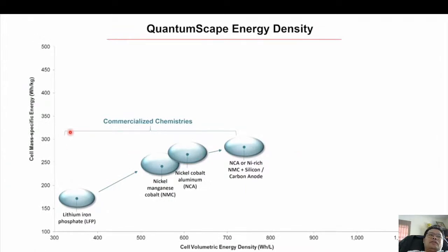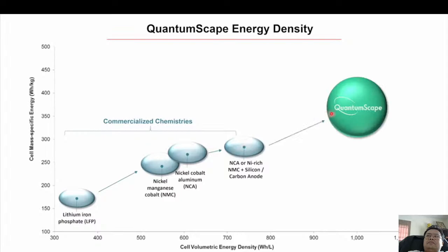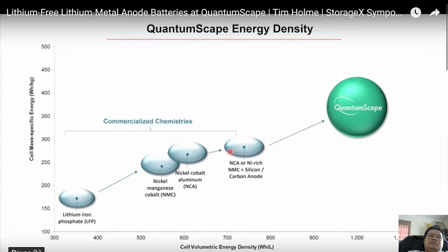So this is a map then of mass-specific energy density, or watt-hours per kilogram, on the y-axis, and volumetric energy density on the x-axis, showing the range of commercialized chemistries from lithium iron phosphate, or LFP chemistries, which are low energy density but low cost, to what's more common in electric vehicles, at least the ones outside of China, using an NMC or as Tesla uses NCA cathodes. So these batteries are going to improve by, we're projecting several percent per year as you go to more nickel-rich cathode chemistries and include more silicon on the anode. But what we're hoping to enable is really a pretty impressive change relative to what's typical in batteries.